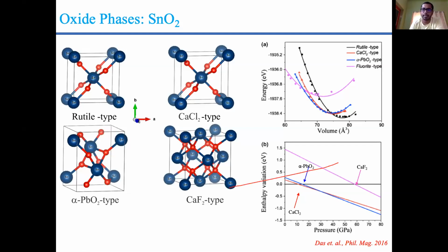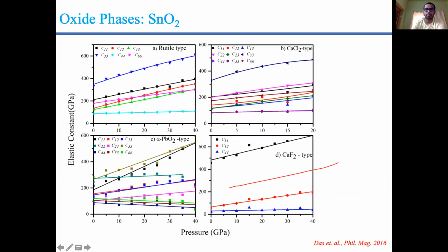by the common tangent method. I also applied what is called enthalpy crossover, where the difference of enthalpy is plotted with respect to the rutile phase. This black line is the rutile, and these crossover points denote the transition pressure. So our transition is reported as rutile to CaCl2 to alpha PbO2 to CaF2. Later, here again the elastic constants are plotted against pressure within their stability range.